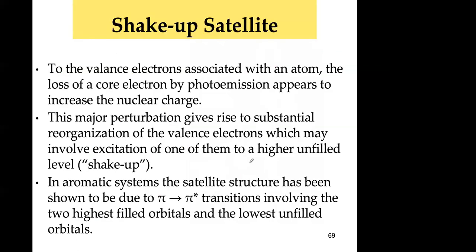Then the shake-up process. I need to make a picture here. The shake-up process is really associated with a π to π* transition, meaning that, for example, this is from the 1s level, and you have another level here, which could be the HOMO, and a higher level that is a LUMO, and you hit this system with X-rays. This internal electron will go out with a kinetic energy. So this electron has a kinetic energy.